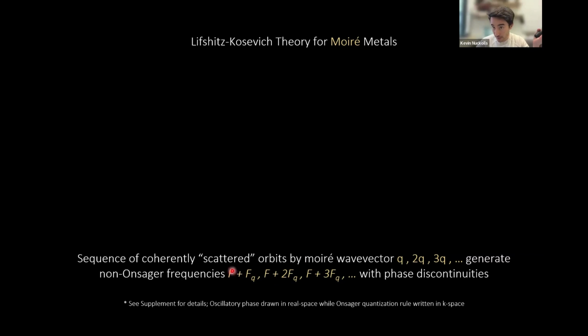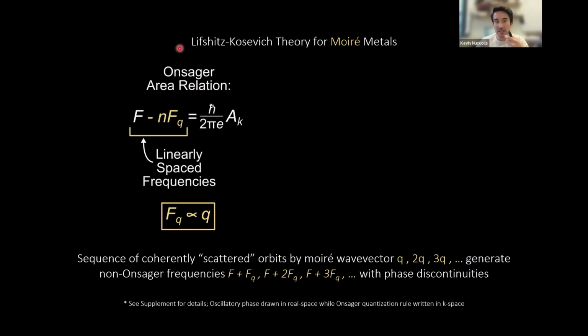that look like the frequency of the pocket plus this anomalous frequency, plus 2 frequencies, frequency plus 3 frequencies, with phase discontinuities. So in order to see that, the Onsager area relation is now affected with this new term that makes sure that this is no longer an Onsager relation. So the frequency is no longer proportional to the area, but it produces a linear set of frequencies where this extra frequency component is proportional to Q. So for Q to be super, super small, the Moiré wavelength is very, very long, we should recover the crystalline Onsager relation. And indeed, this factor goes to 0, and so we recover Onsager's relation.